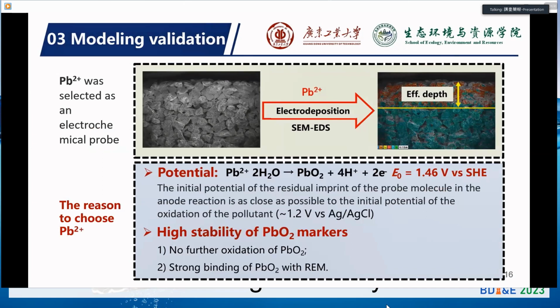So we need to find a probe. It's the core of the process. We compared a few available probes and found lead to be the optimum candidate, for two reasons. The first is that it has an appropriate reaction potential: this is the starting potential for oxidation of most micropollutants. The second benefit is high stability. There will be no further oxidation of lead oxide, and the generated lead oxide has strong binding with the REM.